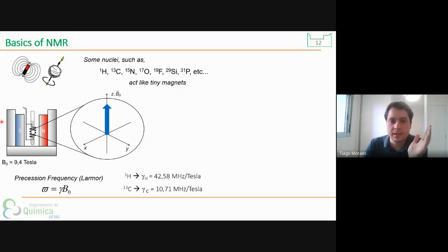So here, it's easier to understand how we detect the signal when we think about the total magnetization in the sample. So in blue here, I represent the total magnetization in the sample. When we apply the radio frequency pulse of 90 degrees, for example, the magnetization goes from here to here. And this position is not stable. So the nuclear spin will precess and return to the equilibrium position. And this return occurs with the precession of the nuclei. So this total magnetization will precess in this way here.